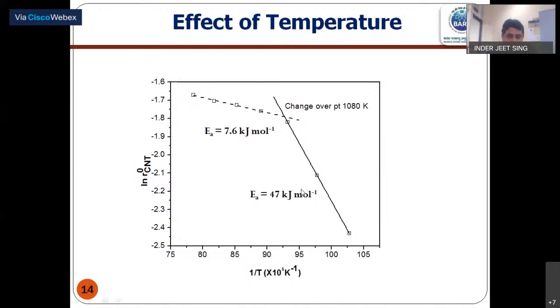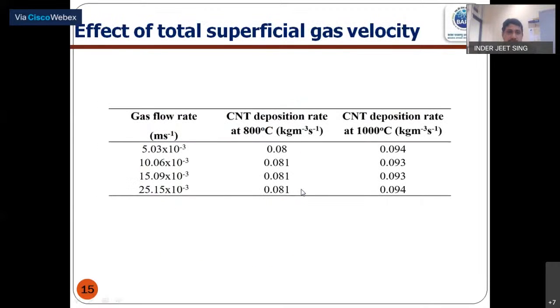Now after getting this impression, we studied the superficial gas velocity effect, and we are seeing that at these two temperature regimes, one low and another high, there is not much effect of the superficial gas velocity on the deposition rate of the CNT. So that means the external mass transfer control is not there.